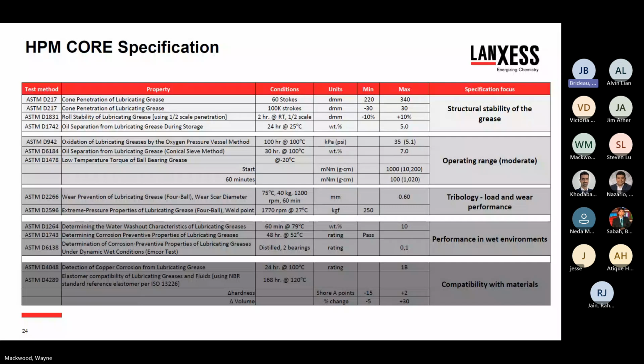So we've done this, but many of the tests look the same as the GC-LB, things like oil separation and storage. Now, we use a different low temperature torque test. The one in the GC-LB uses a tapered roller bearing. We use the ball bearing D1478 test, which we believe has much better precision and more relation to actual operation in the field.